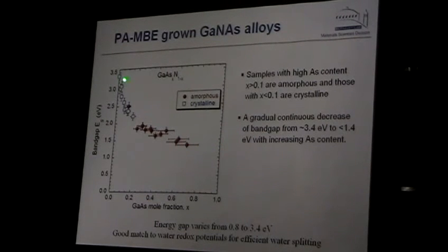It seems to work close to gallium nitride. You see, there is this drastic reduction of the band gap because the arsenic level is so high. So this is a drastic reduction. However, what's happening when you try to change composition to go to higher arsenic contents is that the material breaks down and it's amorphous.